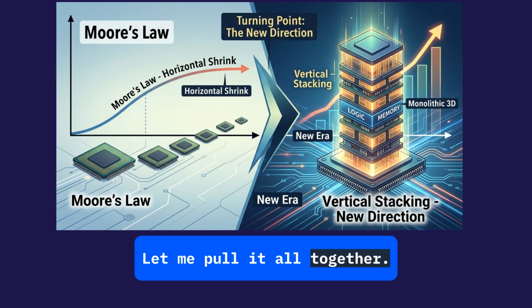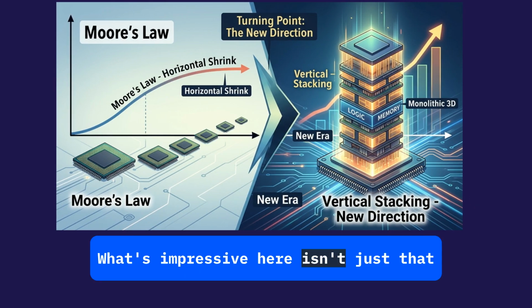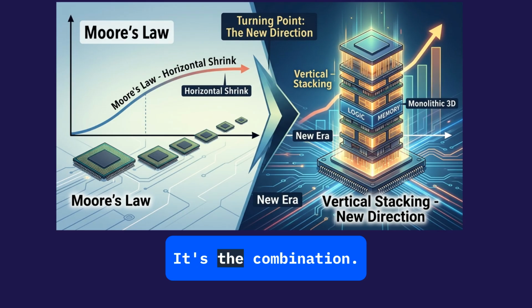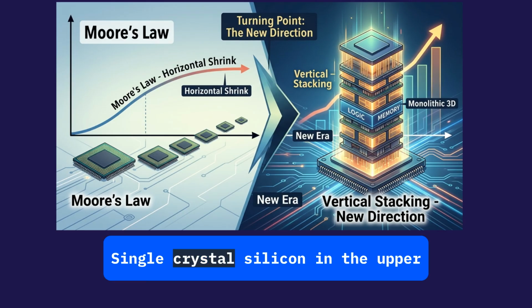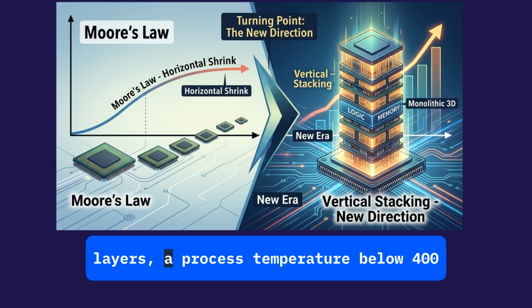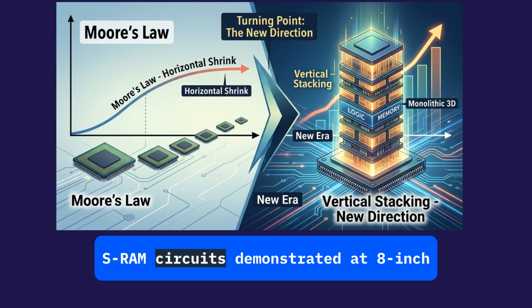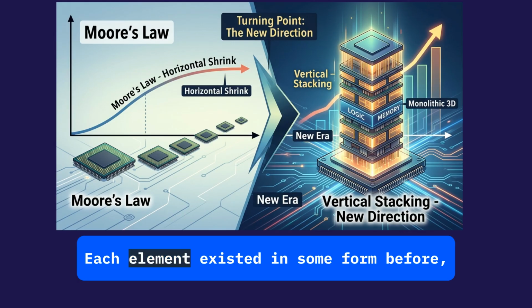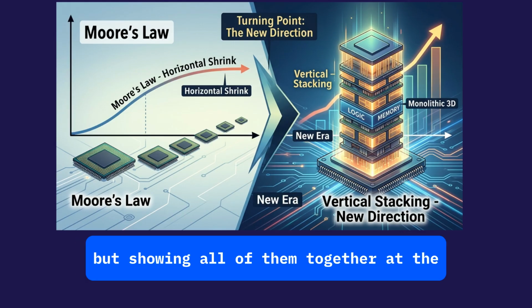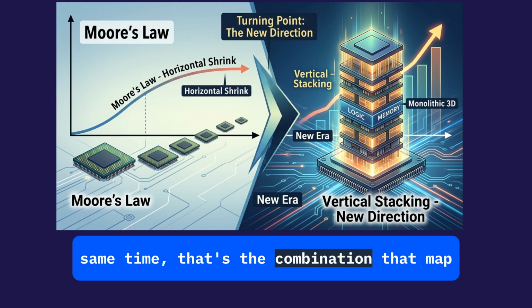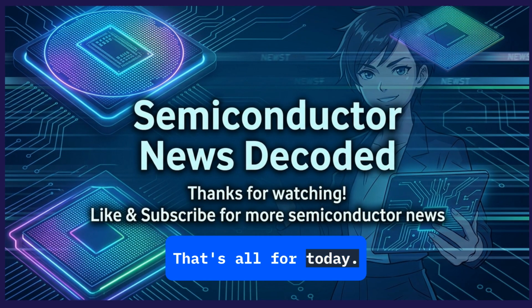Let me pull it all together. What's impressive here isn't just that it's 3D. It's the combination. Single crystal silicon in the upper layers, a process temperature below 400 degrees, with bonding below 200 degrees, 3 stacked layers, working logic and SRAM circuits, demonstrated at 8-inch wafer scale. Each element existed in some form before, but showing all of them together at the same time, that's the combination that matters. That's all for today.